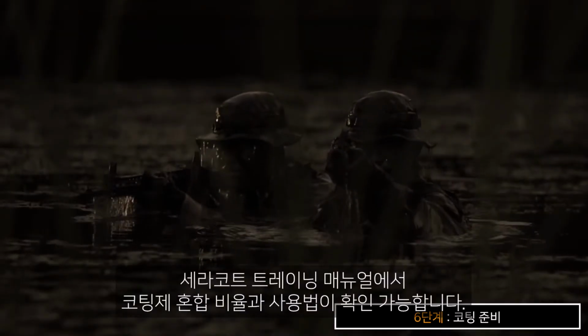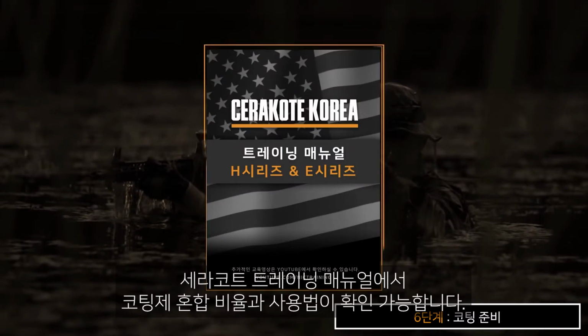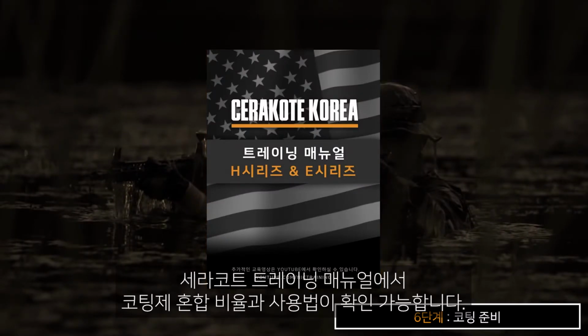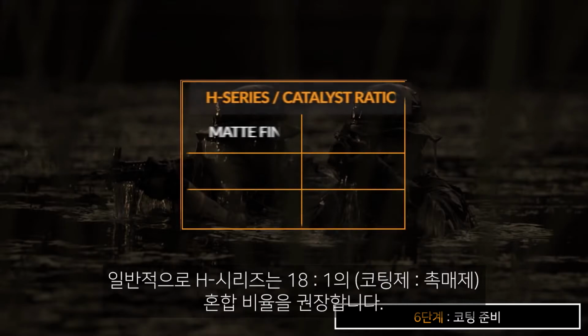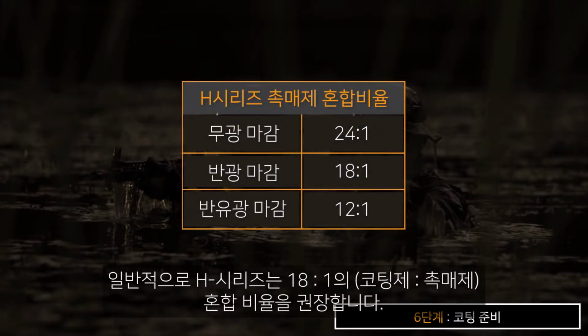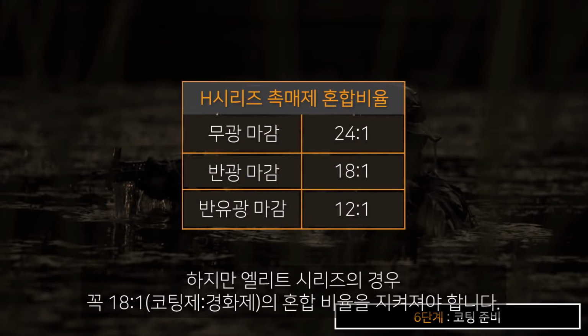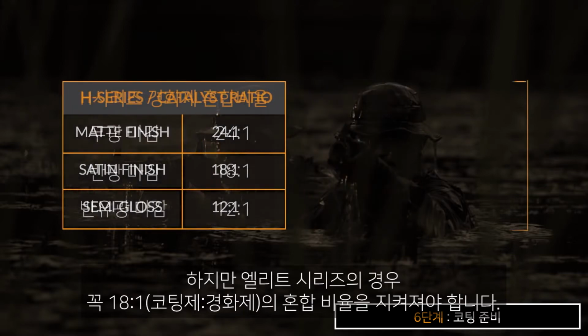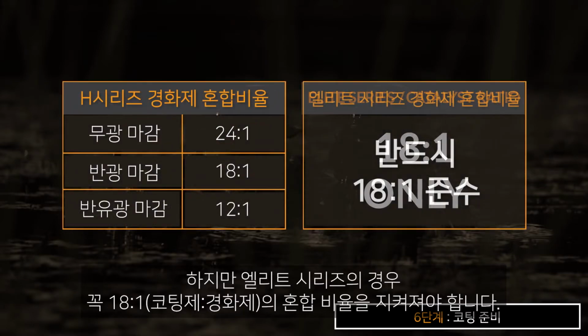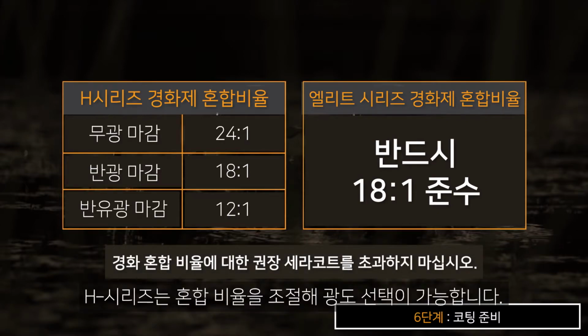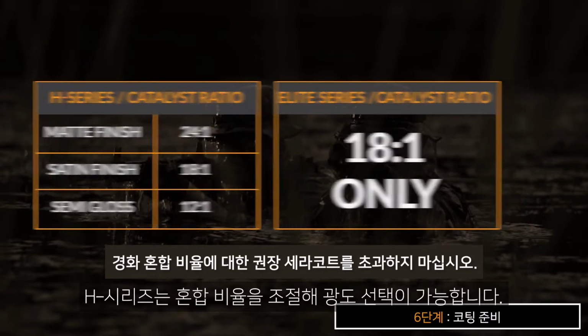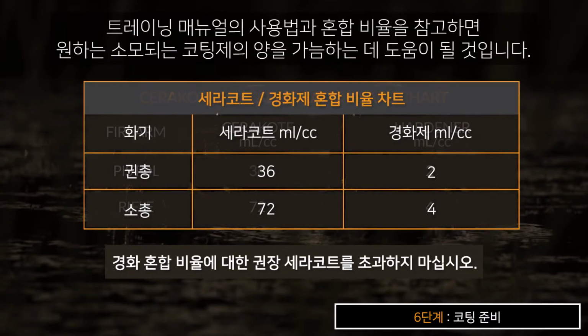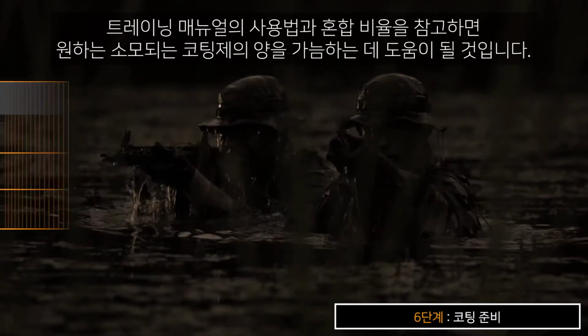Usage and mixing ratio charts are available in the Cerakote training manual at Cerakote.com. An 18:1 coating to catalyst by volume mix ratio is recommended for most H-series, but take note, Cerakote Elite Series requires an 18:1 coating to catalyst by volume mix ratio. However, for H-series, other ratios may be used to achieve lower or higher gloss levels. The usage and ratio charts in the training manual will help you determine the correct amounts for your desired finish.